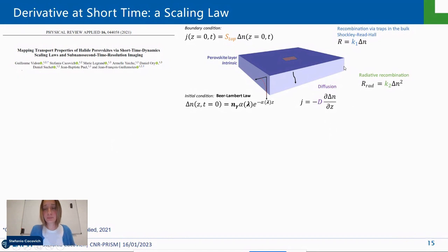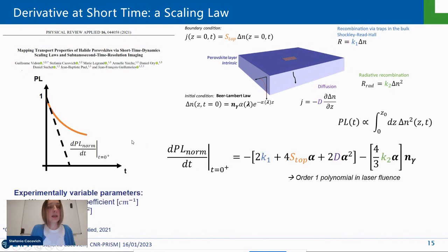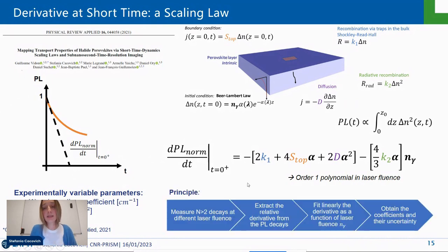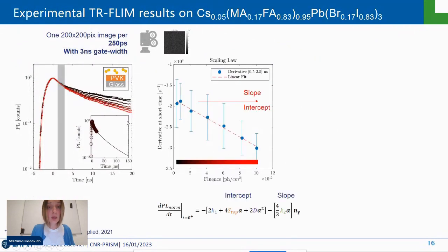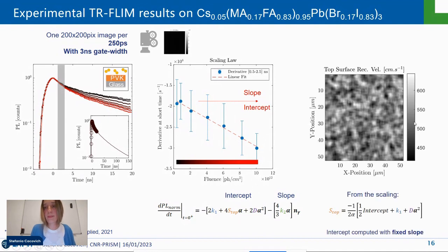So basically it started from the drift diffusion equation, but then what he has done is to work on the derivative of the PL decay at very short time. In this way, he could solve an order one polynomial expression in laser fluence. So this allows us to simplify the fitting, as we have this scaling law, and from the intercept and the slope of this scaling law, we can access different physical parameters.